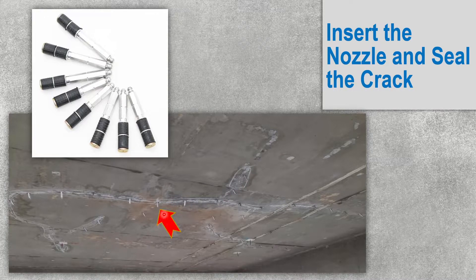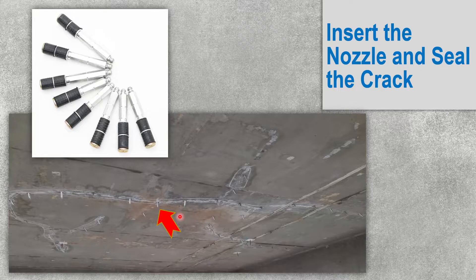You have to insert nozzles into the crack. The gap between nozzles is based on the pressure and method being used for injection, and you should also refer to the supplier's specifications. Depending on the requirement, the spacing may be at 200mm or 300mm intervals.